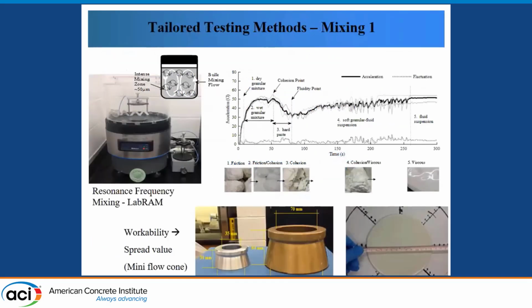In the first phase of the investigation, we use the resonance frequency mixer because it provides high mixing consistency in short time and quality of particle dispersion without the use of any mechanical mixing tool. To the right, there is a graph of acceleration versus time, which is complemented by the picture shown underneath. It shows the change from wet particle clumps to a homogeneous UHPC paste mix. Due to the limited mixing volume, a mini flow cone has been designed and used for measuring the spread.